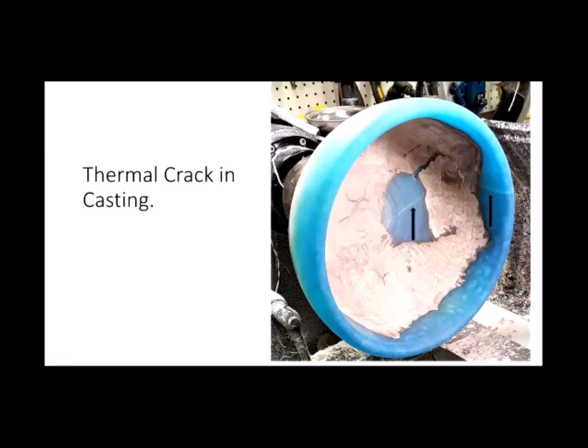All right, so things don't always go well when you use resins and epoxy, and you learn by your mistakes. This was the first nested set that I did. And I used the polyurethane resin, and this is after the repair had been made. But if you look at these two arrows here, there's actually a crack in this bowl. When I took it out of the pressure pot, it was probably a little over an eighth, maybe almost 3/16 at its widest point. And it extended from the rim all the way down into the middle of the bowl.